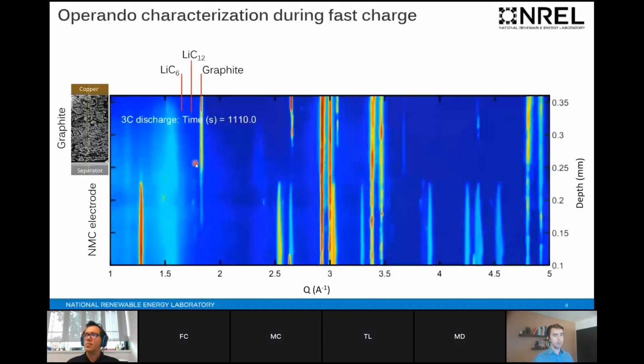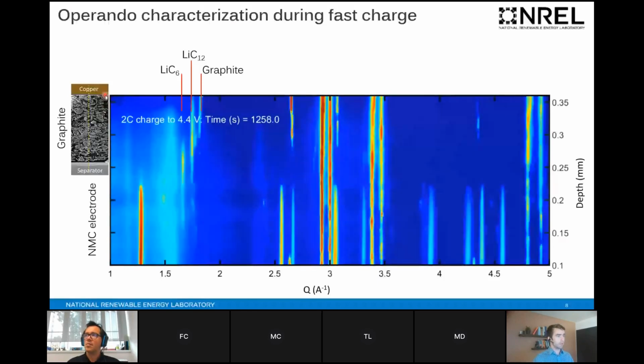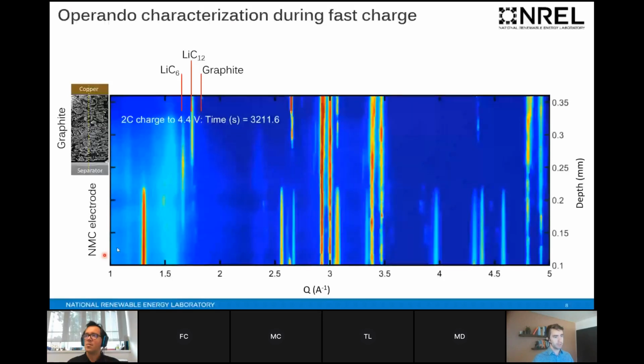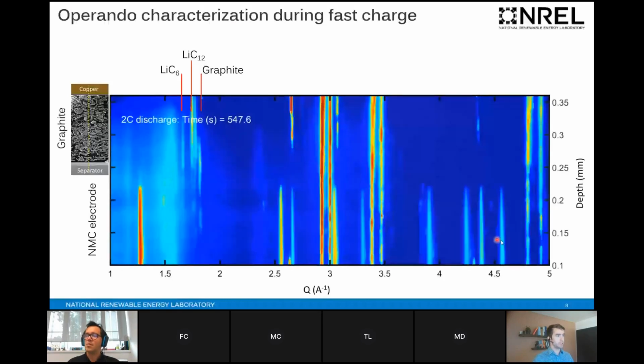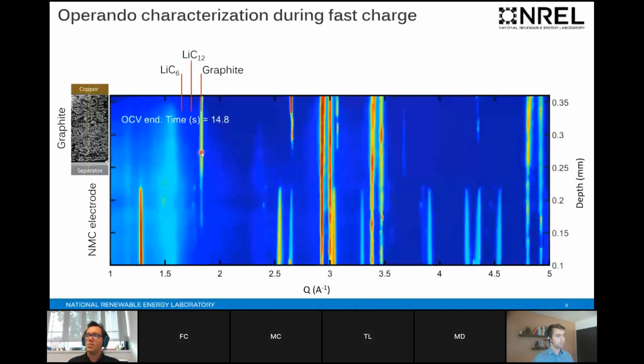And you can see the y-axis is depth. So up here is the graphite. You see the graphite peaks shifting over and back. And here there's a lot of NMC peaks, but I'm not going to talk about those. I'm just going to focus on this data that we collected on the graphite as a function of depth.